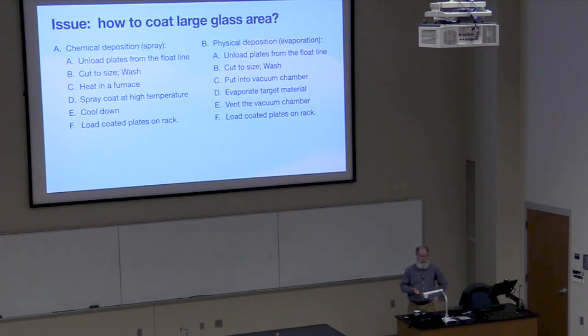Libbey-Owens-Ford used to operate an evaporation process, which was pretty amazing. Once again, you have to unload the plates from the float line, cut them, you wash them, put them in a vacuum chamber, which takes time to pump down, and costs a lot of money for those big vacuum pumps. Then you coat your glass, you vent the chamber, move it out. So it seems like kind of a slow process.